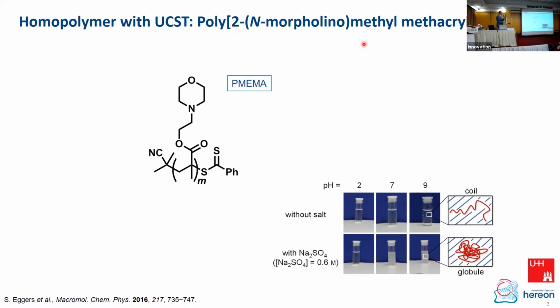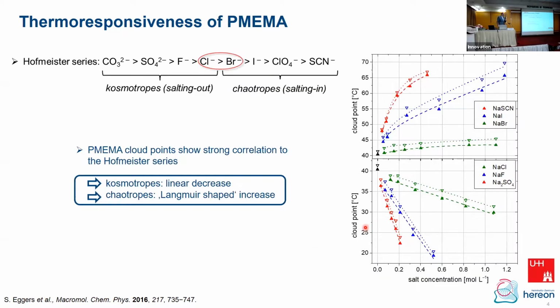This monomer, N-morpholinoethyl methacrylate, is an interesting monomer which shows stimuli-responsive properties when you use it as a polymer. You see here solutions under different conditions. We have different pH values, and in one case without salt, and in another case we add sodium sulfate in a certain concentration, and you see that the transparency of the solution is affected depending on the conditions you use. So this seems to be stimuli responsive. A lot of studies were carried out, but I keep the story a bit short here.